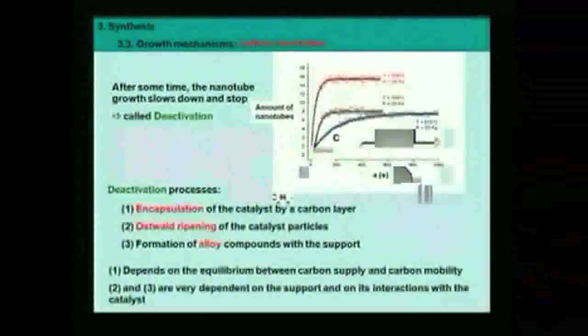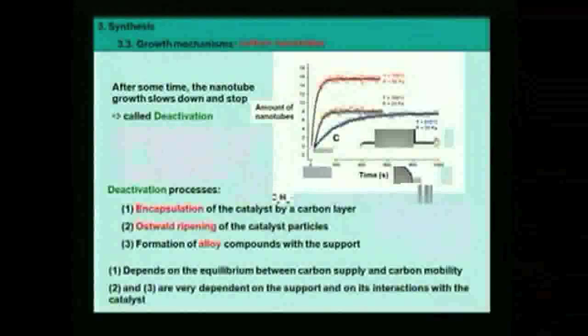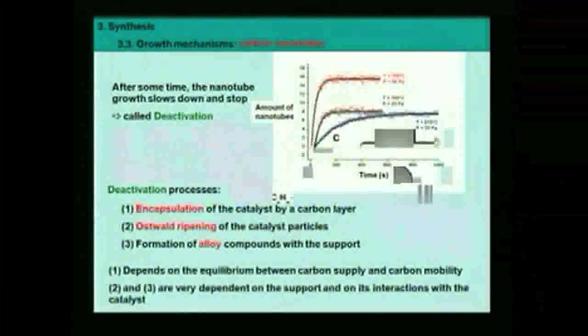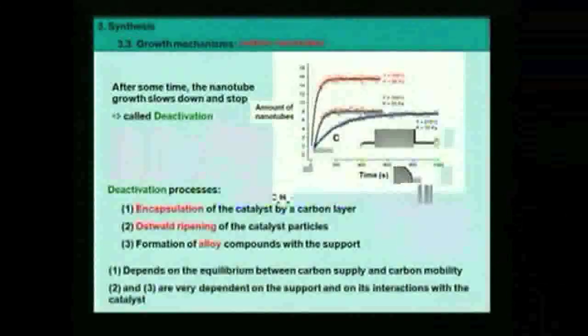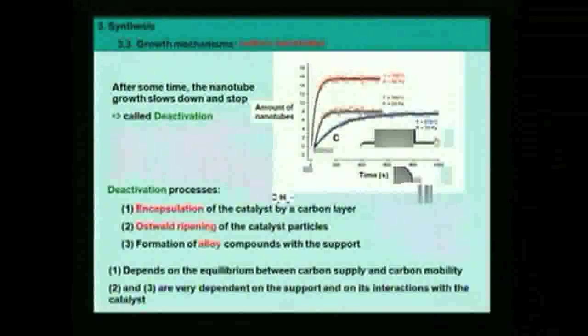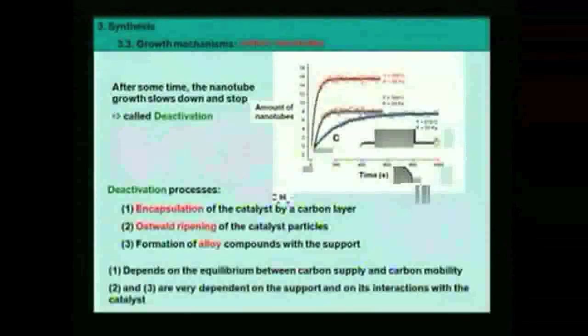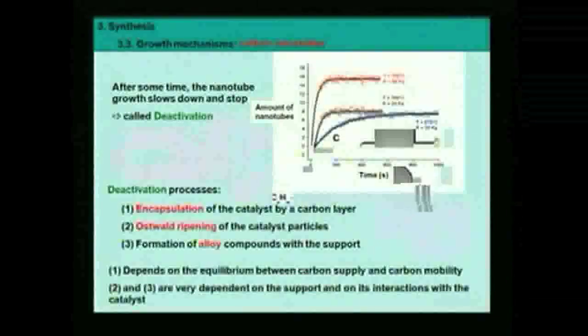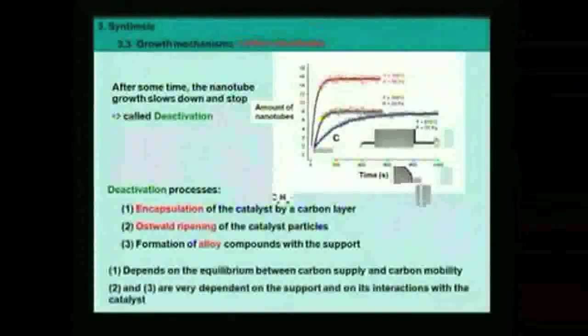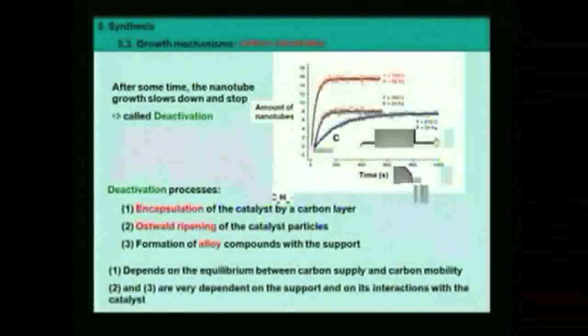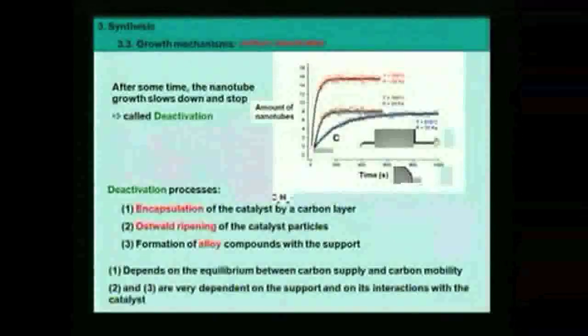The other typical deactivation of catalyst in heterogeneous catalysis is that the catalyst reacts with the support. The formation of silicides, the formation of silicates are very important problems in heterogeneous catalysis. So this is another kind of deactivation. Here, in the case of a catalyst particle, there is another phenomenon, which is called Ostwald ripening, which is the fact that small particles are less stable than large particles, and the small particles will disappear and form larger particles. We will see that in detail.